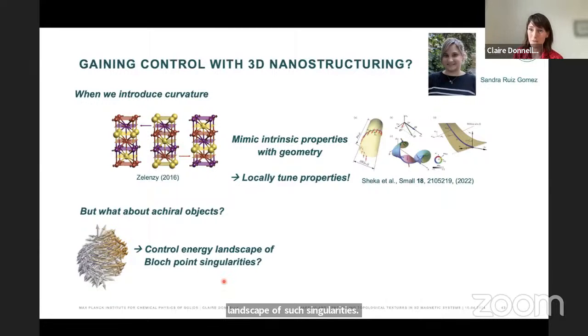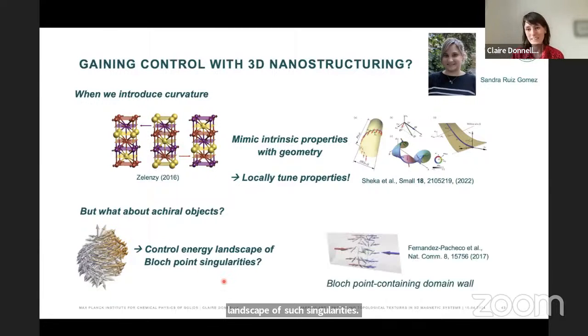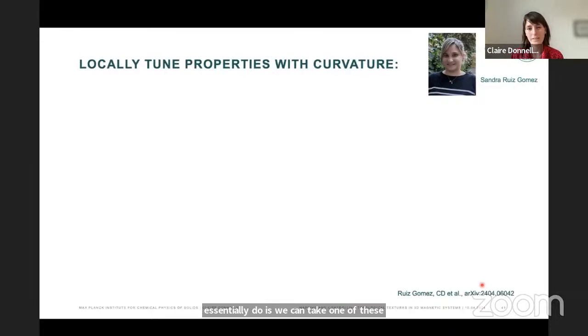Now, what we can actually make use of in this project is the fact that, luckily for us, when we go to three-dimensional magnetic systems and indeed cylindrical magnetic nanowires, we automatically have a system that hosts these Bloch point domain walls. And so what we essentially do is we can take one of these nanowires which hosts Bloch point domain walls, and we can introduce curvature.